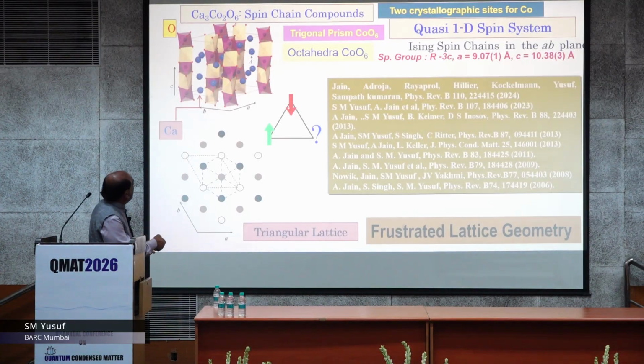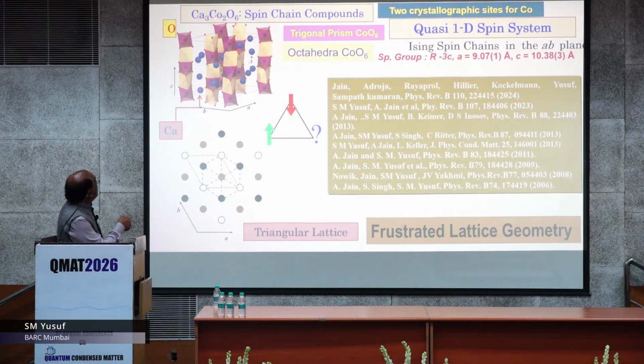So first I start with the triangular lattice. So how is it? This is the real system. This is a compound oxide material where this is the magnetic atom. There are two cobalt sites. They form an Ising kind of chain because this is ferromagnetically aligned. So, ferromagnetic chains. By these three chains, they are forming a triangular lattice. So that means in a planar structure, it is my triangle and there is an antiferromagnetic exchange interaction. Though along the line there is a ferromagnetic, but between chains antiferromagnetic.